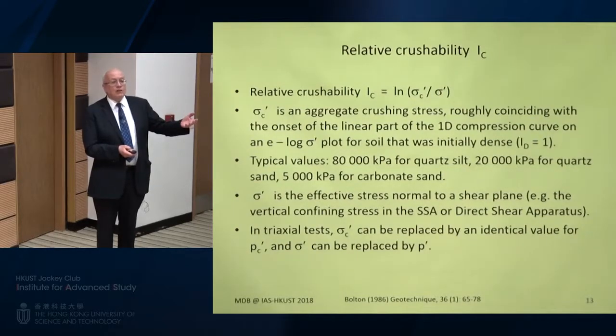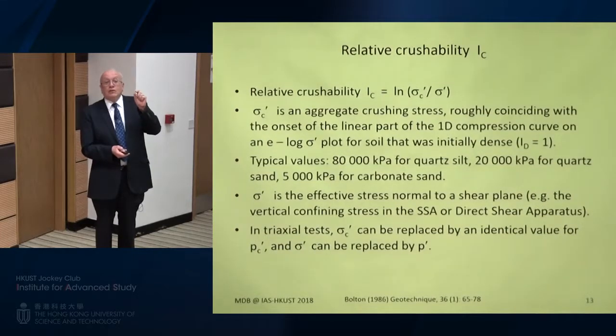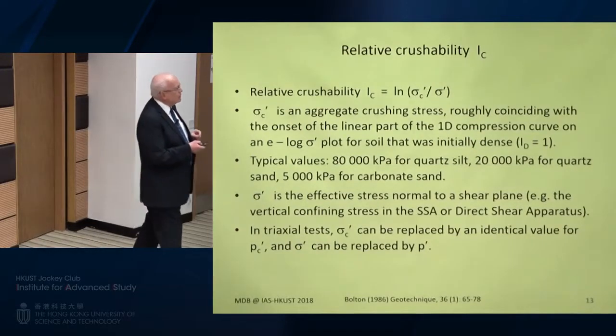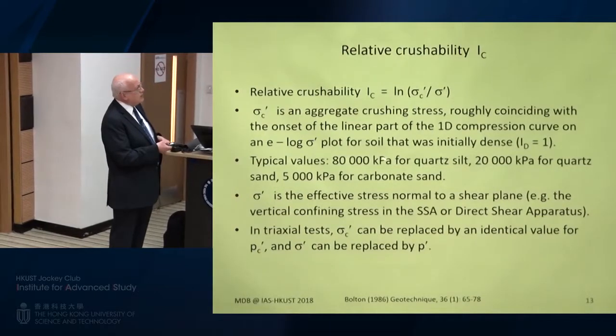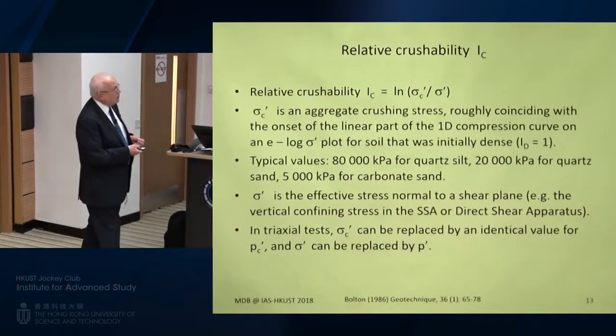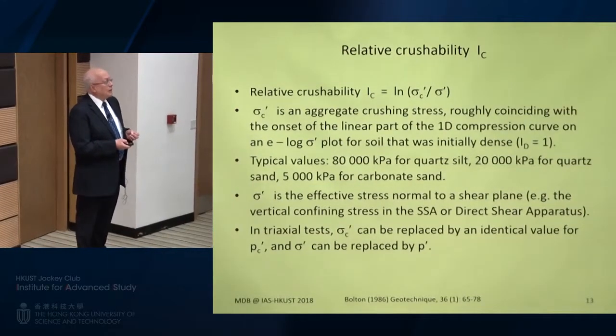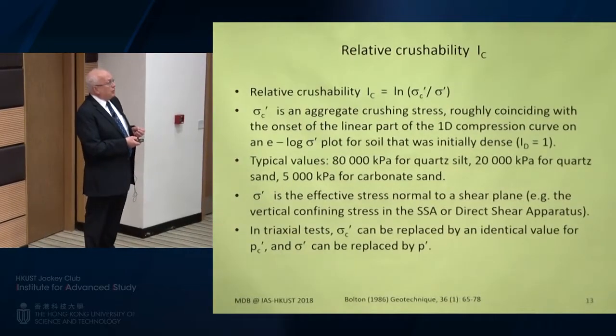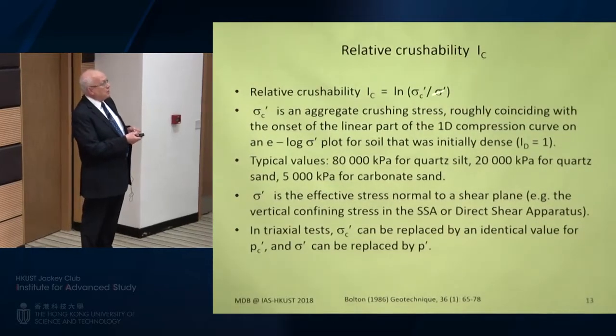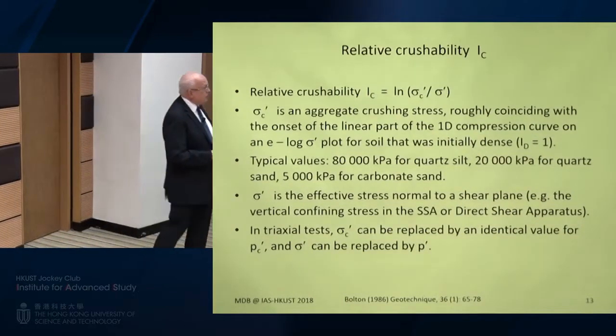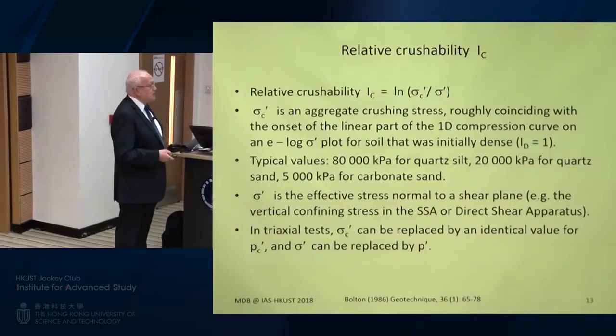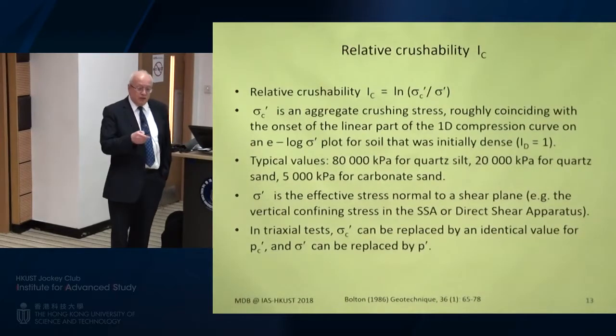We know this with regard to rods and fibres because glass fibres and carbon fibres are much stronger because the flaws in them that would give rise to brittle fracture are obviously much smaller, and so their brittle strength is greater. And so for quartz silt, as you'll see later, a much bigger value, 80 megapascals, turns out to be appropriate. And much less for broken shell fragments. And so this is my apologia about using sigma dash as the vertical effective stress in a shear box, and sigma dash C similarly as the parameter that goes with it, which is the crushing stress.